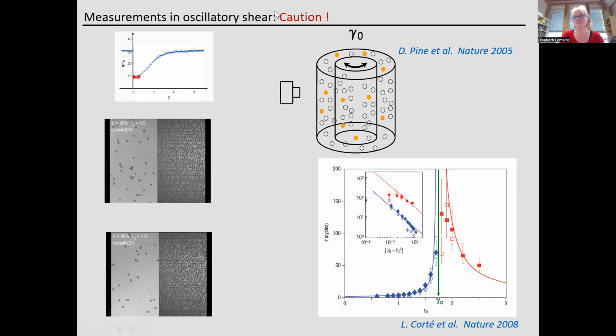So my advice is to be very cautious if you make oscillatory measurements with a non-Brownian suspension. This complication comes from the fact that non-Brownian suspensions are athermal systems. So all the microstructure, all the particle organization is controlled by the flow itself, and there is nothing to bring the suspension back to its equilibrium state. So there is no equilibrium state, in fact.